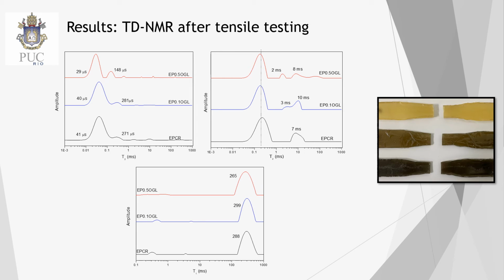And here we have the same results of TD-NMR experiments, but now after the tensile testing in the epoxy resin. So analyzing the behavior of the samples after the mechanical test, it becomes evident that even after mechanical stress, the compositions containing graphene have shown greater mobility as a function of the filler concentration, especially in the mobile region, while the rigid fraction is practically unchanged.